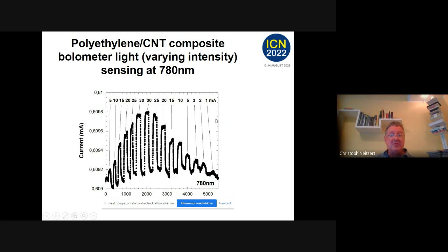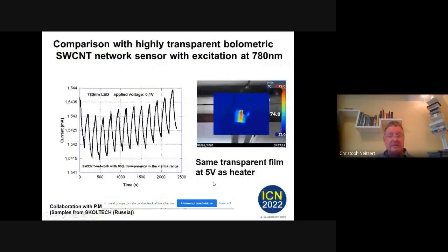And here we change the intensity of the light just by changing the current of the LED, 5, 10 until 30 milliampere, going down to 1. And here you see we still have a dynamics which is interesting, but it's a little bit noisy. That is like kind of following, maybe because of temperature. This is the alternative to the carbon nanotube with polymers or epoxy, and it's a pure single-wall carbon nanotube network.